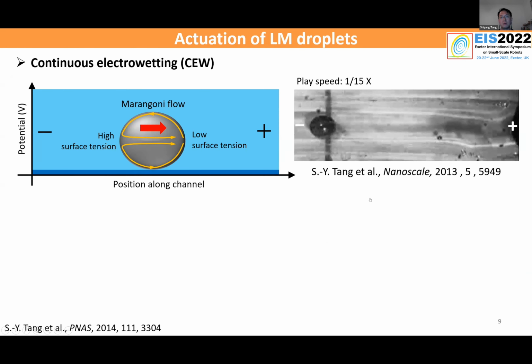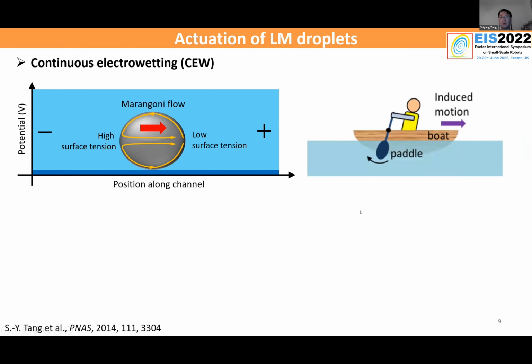So you can imagine. Here I coat the surface of the liquid metal with some metal particles to show the formation of the Marangoni flow upon the application of external potential. Here you can see that the particles on the surface can be stripped off, so the droplet will become bald. You can imagine this as if you're trying to paddle a boat on a river. The paddle behaves like the surface of liquid metal, which generates the flow. So in this case, the flow will drive the boat